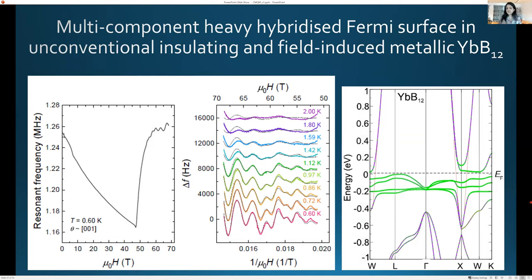However, what is unique to this type of insulator is that the bulk insulating behavior of these materials is contradicted in some sense by the bulk Fermi surface that one sees from quantum oscillations in these materials. So the way we're defining this new class of unconventional insulators is materials in which the bulk is insulating, yet where one sees a bulk Fermi surface. And this is not a property of any other insulator seen before. So in topological insulators, you had bulk insulating behavior, conducting surface, and a surface Fermi surface from this conducting surface.